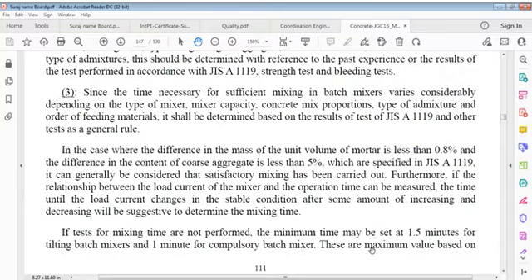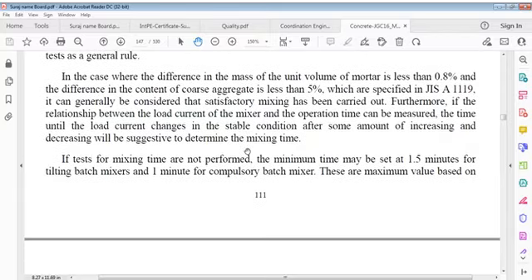Since the time necessary for sufficient mixing in batch mixers varies considerably depending on the type of mixer, mixer capacity, concrete mix proportions, type of admixture and order of feeding materials, it shall be determined based on test results as a general rule. In the case where the difference in mass of unit volume of mortar is less than 0.8% and the difference in content of coarse aggregate is less than 5%, which are specified, it can generally be considered that satisfactory mixing has been carried out.